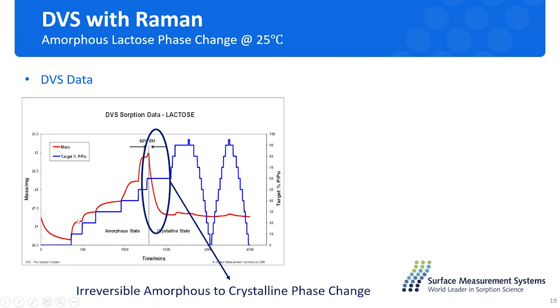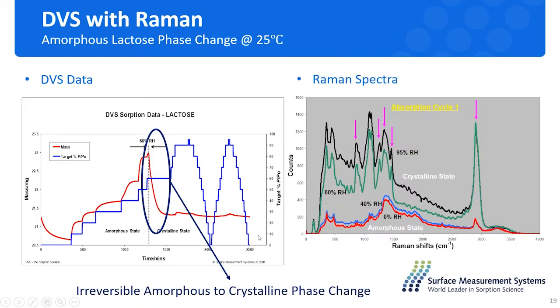What we do with Raman is we take a Raman spectrum at the end of each step when the sample is reaching equilibrium. Then we can get this overlay of the Raman spectra for the sample as well. At 0 and 40% RH, it's a very broad peak in the Raman spectrum, so it's an amorphous phase. And exactly above 60% RH, there are some new peaks showing up here, confirming the crystalline state of the material at higher concentrations of water. So this data shows you the combination of DVS and Raman, giving you a full idea about the solid characterization happening during the moisture sorption and desorption process.